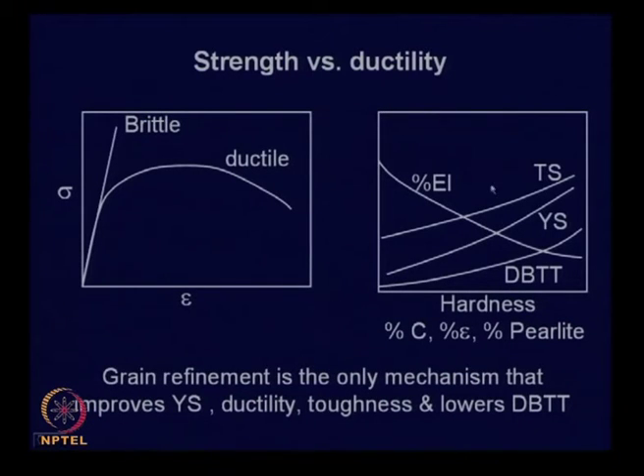One problem that comes up in any of these fabrication processes or alloy elements is that when you improve the strength, its ductile to brittle transition temperature increases. A certain steel which is normally quite ductile at room temperature will be brittle if you test it at a low temperature. The temperature at which this transition takes place is called the ductile to brittle transition temperature, and a high ductile to brittle transition temperature means the material is susceptible to brittle failure at low temperature. Normally, if your strength increases, the ductile to brittle transition temperature also increases.